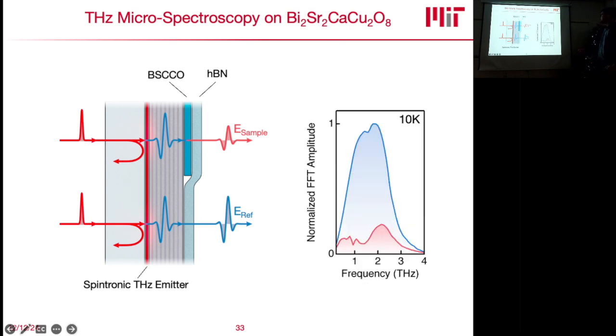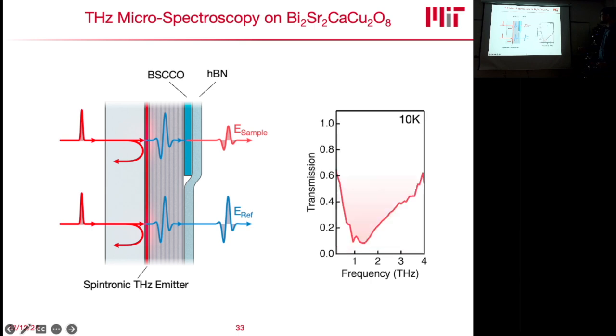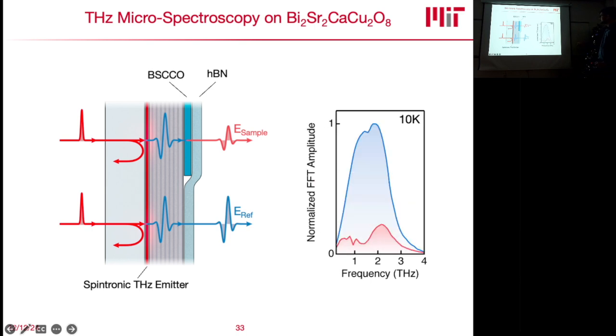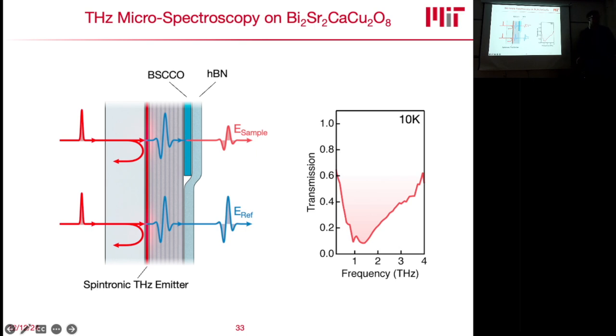And so what we can then do is take the normalized FFT amplitudes of this, so we see this strong suppression. We see these very sharp dips in here as well. We can then divide our sample curve by our reference curve, which gives us our frequency-resolved transmission through the sample. And you can see you get a very strong depression here at around 1.5 terahertz at 10 Kelvin.